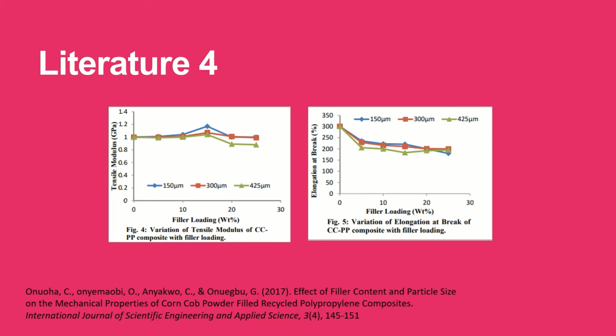Lastly, Figure 5 shows lower elongations at break for the modified samples than for the unmodified samples. It is obvious from the data that elongation at break decreased with increase in filler loading and particle size. Filler incorporation into a polymer matrix increased the stiffness and hardness of the composite. This increase in hardness resulted in decrease in ductility of the material. Hence, as filler content increases, the ductility decreases, thus decreasing elongation at break with filler loading.